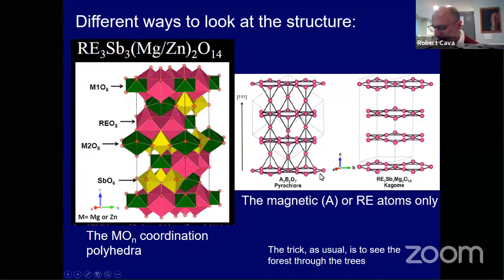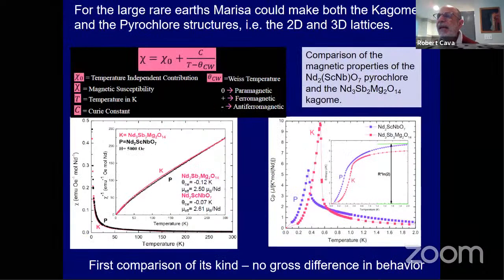So the idea here was to try to find a set of rare earths that would make both crystal structure types. There's a stability region for the Kagome, and there's a stability region for the pyrochlore. If you want to do a direct comparison, you have to find a rare earth system that is stable in both structures. And it turns out there aren't too many of those. Neodymium is the best one, believe it or not. And so we can directly compare the neodymium scandium niobate pyrochlore with the neodymium antimony magnesium Kagome.